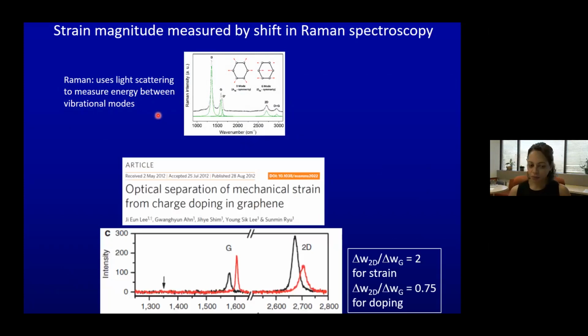and the doping. And actually, there's this really nice paper that came out some number of years ago showing that indeed these G lines and these 2D lines shifted when the graphene was strained. However, they also shift if you change the electrostatic environment of the graphene. Okay, so what we want to do is distinguish between changes due to charges and changes due to strain. And what this paper showed is that you can differentiate these two by looking at the ratio of how much the G line and the 2D line shift.